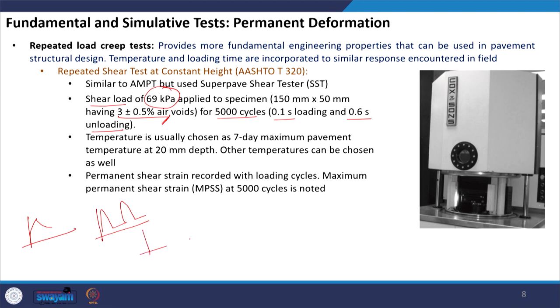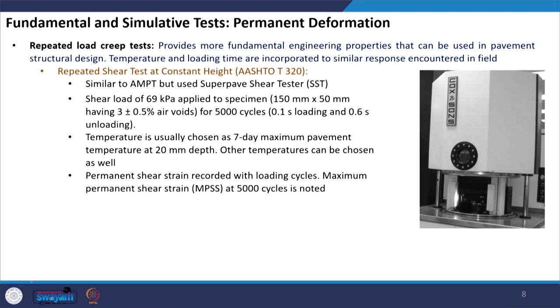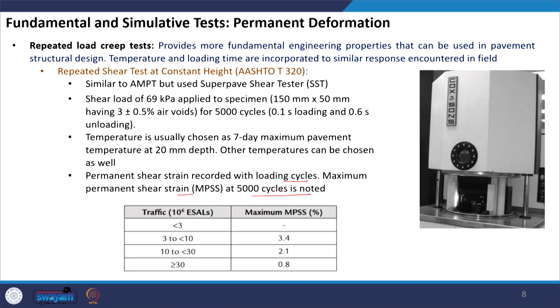Looking at the material response, the strain increases, then after recovery there will be recovery in the material, again the strain increases, again recovery, and so on. We record the permanent strain with loading cycles, and the maximum permanent shear strain at 5,000 loading cycles is noted. A specification table is available corresponding to different levels of traffic, showing the maximum permanent shear strain accumulated in the material after 5,000 cycles.